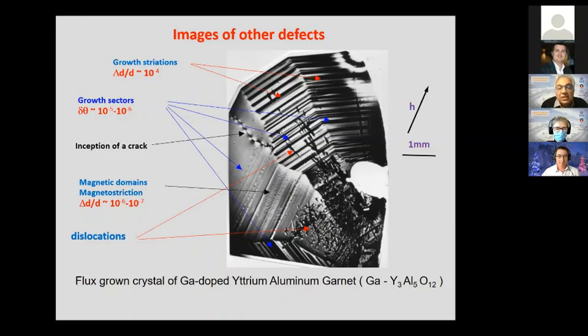You could say this crystal is awful, is full of defects. Actually, it's a very good crystal because the technique we use is tremendously sensitive. That is, growth striations, which appear very clearly, only correspond to a variation of lattice parameter delta d over d of the order of 10⁻⁴. The growth sectors have different orientations in the 10⁻⁵, 10⁻⁶ radians. And the magnetostriction giving this faint contrast of the domains is of the order of 10⁻⁶, 10⁻⁷. So this is a very sensitive technique.